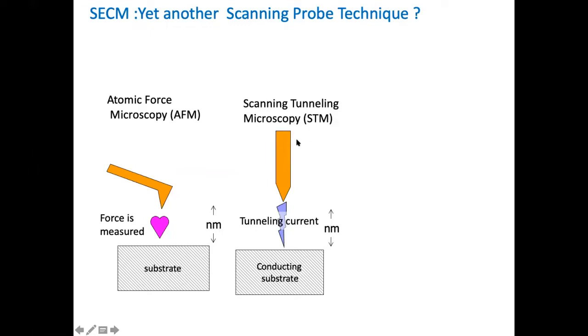One more technique you are all aware of is scanning tunneling microscopy, which is called STM. There are lots of atomic pictures, where we can see atoms of a gold surface. This is done by scanning tunneling microscopy. Here, we bring a tungsten probe near the conducting substrate, and what we measure is the tunneling current. So here, the response is tunneling current. The response is force in the case of AFM.